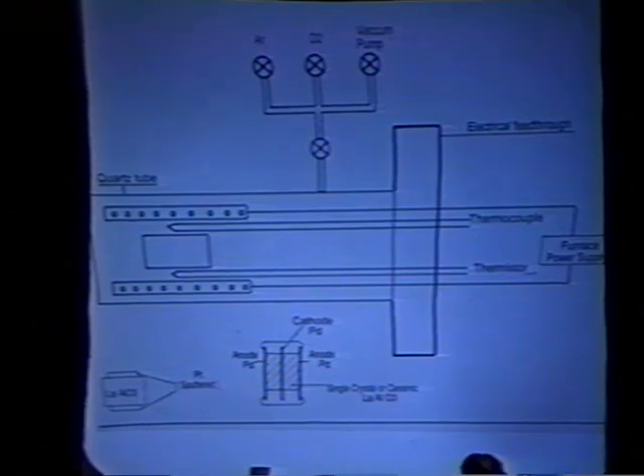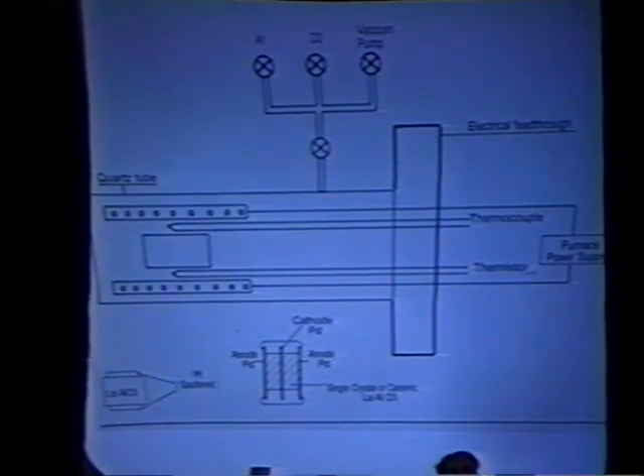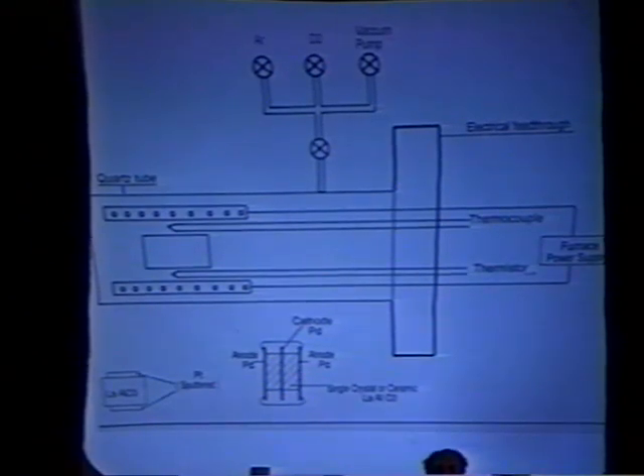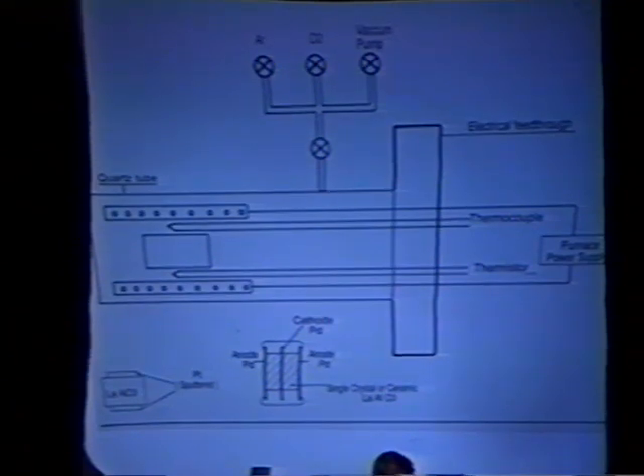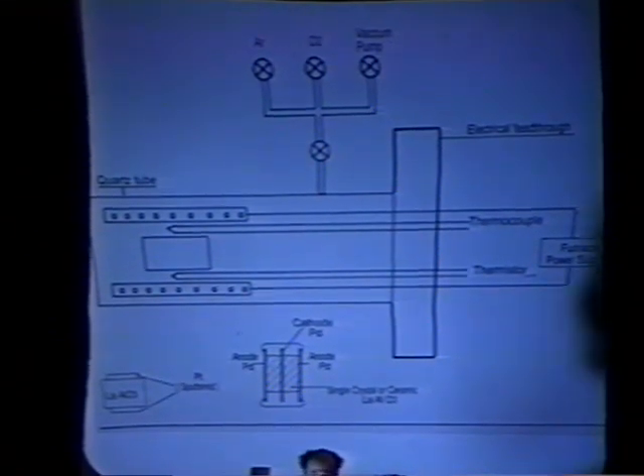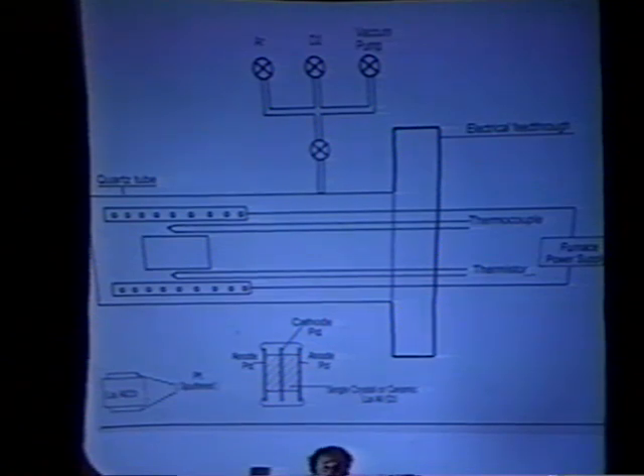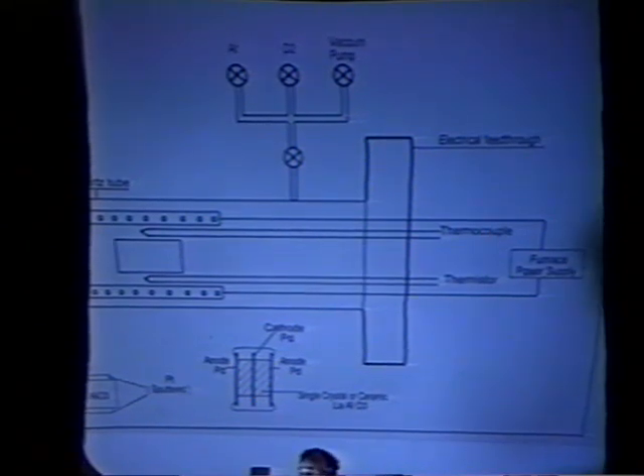So it disappeared. So we use thermocouple for calibration, and then we use the resistivity of the heater itself, of the furnace itself, to deduce the temperature. So we regulate the input power of the furnace and measuring the resistivity will deduce the temperature by calibration. So the data I will show you are with this kind of measurements.